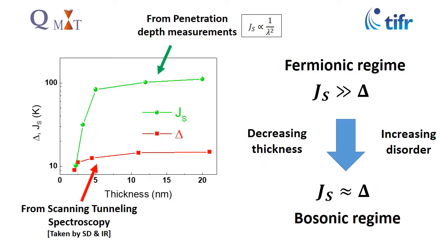To quantify these effects, we have compared two different energy scales. One is the superconducting gap, delta, measured from the scanning tunneling spectroscopy, and the other is J_S, also known as the superfluid stiffness, measured from the penetration depth. As you can see, for the higher thicknesses, J_S is much greater than delta, which is the case for conventional superconductors, but it becomes comparable at lower thicknesses. That is, it becomes more prone to phase fluctuations.